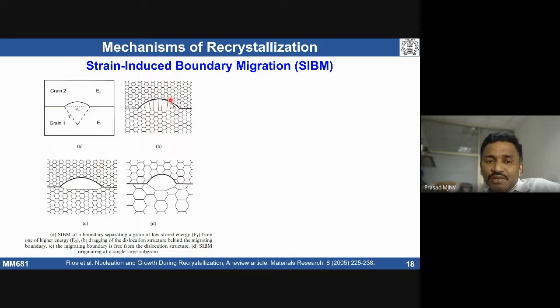With further deformation at high temperature, the subgrains are going to grow, and at the same time we are going to see formation of a strain free grain at the boundary. This is how people explain the formation of a recrystallized grain due to difference in energy between the grains. This is called strain induced boundary migration, because the difference in strain leads to difference in energy, which induces a boundary bulging. Finally this leads to formation of a strain free grain with high angle grain boundary character.